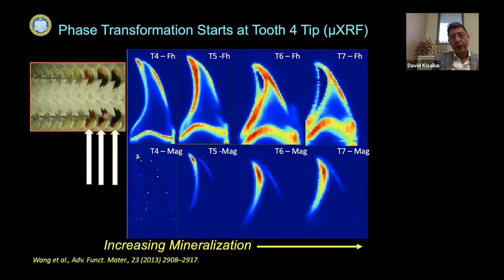Again, I mentioned that the transformation occurs just within a few rows of teeth. So this is just micro XRF showing the ferrihydrite phase that exists in tooth 4 through 7, and the magnetite that starts to form at the tip of tooth 4 and propagates down and across the teeth, consuming the ferrihydrite to form the magnetite that eventually is in the fully mineralized teeth.